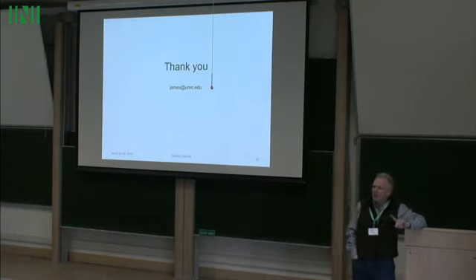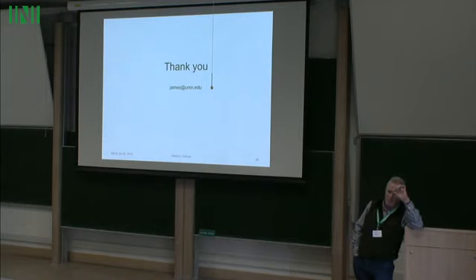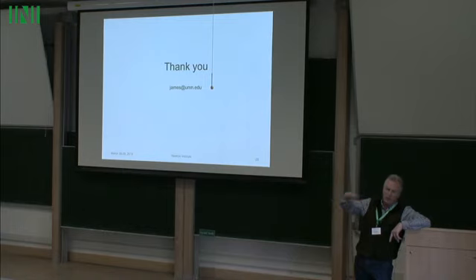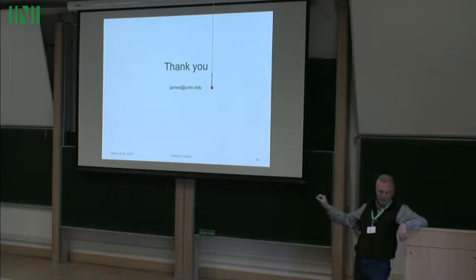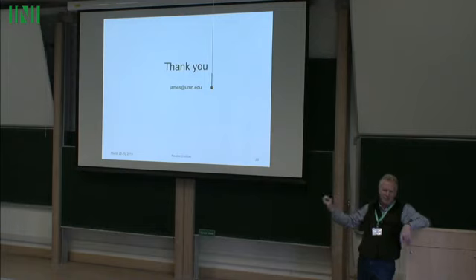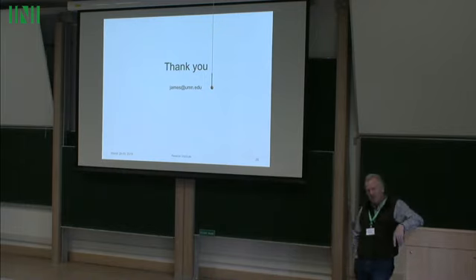And so your question is if you made the amplitude smaller and smaller, right? So we did do that. Or the wavelength longer. That would have very little effect because most of the transformation is occurring quite quickly. We were oscillating the temperature in those pictures maybe 5 degrees C, something like that, but the transformation was occurring within a 0.2 C hysteresis, or 0.5 C hysteresis, or maybe 1 degree hysteresis. We measure various things but it's still very small. So that's much smaller than 5 degrees. So much of the transformation was occurring in a very small interval. But it would be quite hard to freeze that interface because, as I say, the hysteresis is so small.